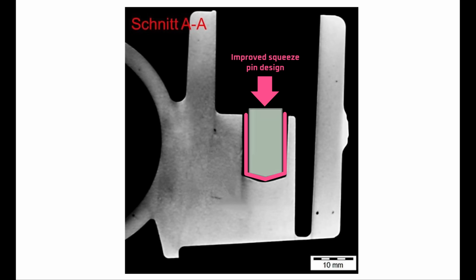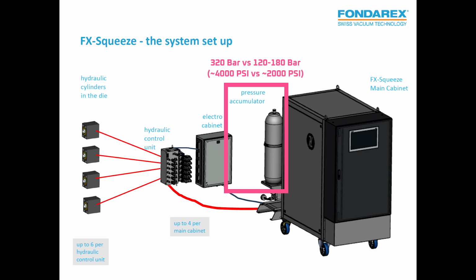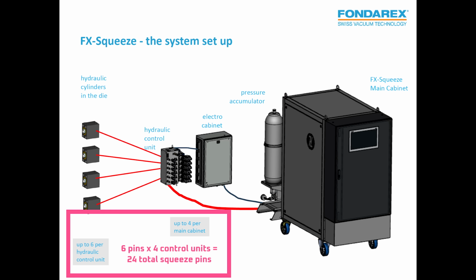for their squeeze pins. The pressure accumulator that Fondarex provides with FX Squeeze is capable of 320 bar, or more like 2 tons of pressure per square inch rather than 1 ton. That allows for the control of up to 24 squeeze pins rather than 6, which dramatically increases the force of FX Squeeze over a conventional pin system and the number of locations within the die that force can be applied.